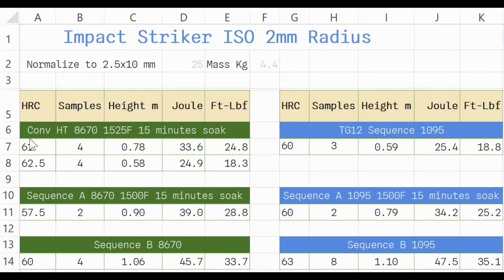But if you recall just a moment ago, I extrapolated 60 Rockwell for conventional heat treat and got about, say, 28. But now for this, only at 57.5, which would be about 2.5 Rockwell less, the foot-pound was about the same. I expect, because again, the more you go toward iron, or ferrite, in your sample, then you don't keep on increasing. You need the strength. You need actual martensite, a lot more martensite, rather than just ferrite.